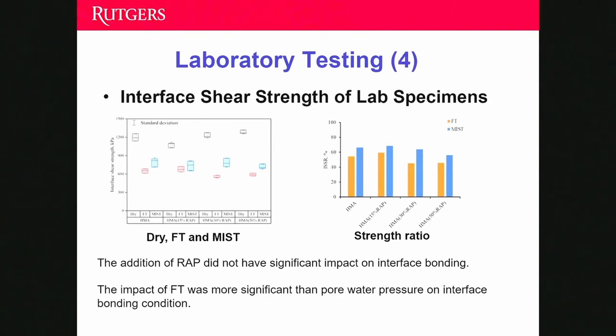And for the interface shear strength, interestingly, we didn't find a significant impact of the RAP on the interface bonding. The reason we guess is because when we mix the RAP with the new HMA, the actual RAP material distributed exactly on that interface was random and unknown, which could be a possible reason. And similar to the IDT strength, we found that the impact of freezing thaw was more significant than pore water pressure on the interface bonding condition.